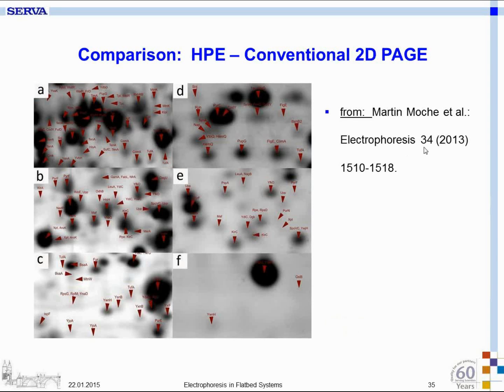That was a technical paper in the year 2013, Martin Moche and colleagues, and there you can find also statistics and all these comparisons between the traditional, conventional vertical thicker gels and the horizontal gels. These were the same areas of one gel shown from the vertical and from these thinner gels, and you see immediately that the resolution and the sharpness of the spots is so good that you detect many more proteins than in a conventional system.